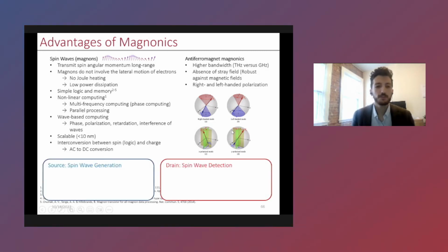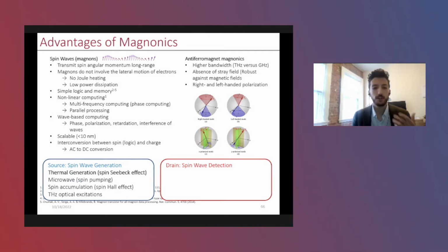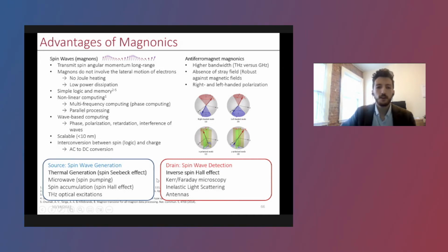And so there's been a number of different ways that the community has both created and detected spin waves, both in incoherent and coherent ways, such as using optical techniques or spin pumping and their complementary detection mechanisms, but also incoherent techniques such as using the spin Seebeck effect and the inverse spin Hall effect or the spin Hall effect to generate spin waves. So in today's talk, we'll mainly be talking about thermal generation via the spin Seebeck effect and incoherent detection using the inverse spin Hall effect.